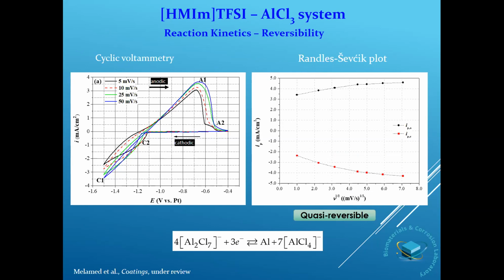The reaction kinetics was evaluated based on the effect of the potential scan rates on the A1 anodic peak and C1 cathodic peak current densities. Figure B shows the peak current densities dependence on the square root of the scan rate. The plot seems to have 2 slopes. Hence, the current seems to be controlled not only by charge transfer, but also by mass transport, namely diffusion of the electroactive species. This coupled effect reflects a quasi-reversible reaction. The fact that the line in B does not intersect with the origin, as expected from a simple diffusion control process, indicates a contribution of a side reaction in the non-purified ionic liquid.